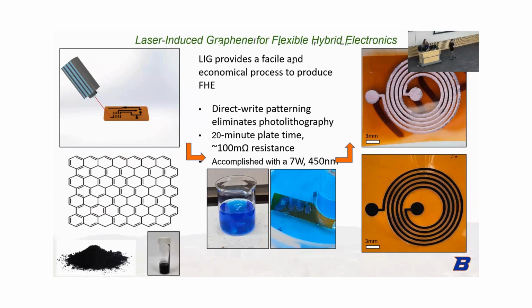You have good electrical and thermal conductivity, really strong in-plane strength. Laser-induced graphene is similar to that, but it's mostly bulk graphitic regions with a lot of voids. And then around those voids, you have monolayer and multi-layer graphene. The way that you synthesize this material is implied in the name laser-induced graphene. You just shine a laser on an appropriate carbon-containing substrate, and really that's about the stipulation. Most carbon-containing substrates. So in literature, this has been done on bread, paper, cardboard, silk, coconuts, Kapton, which is a polymer sheet, flexible sheet. And that choice of substrate is what's really interesting.